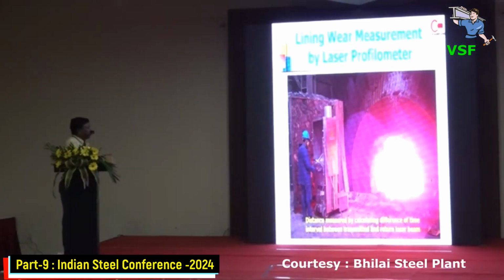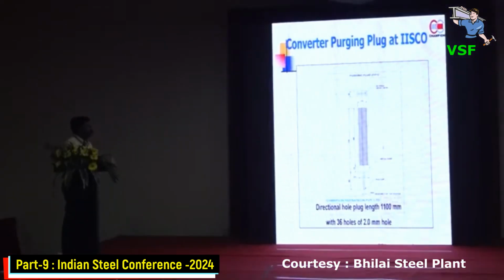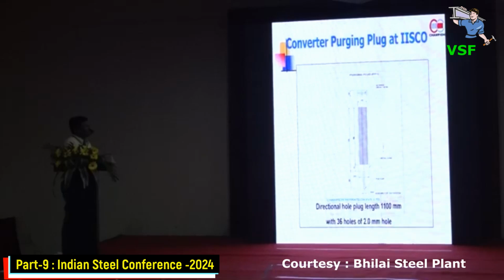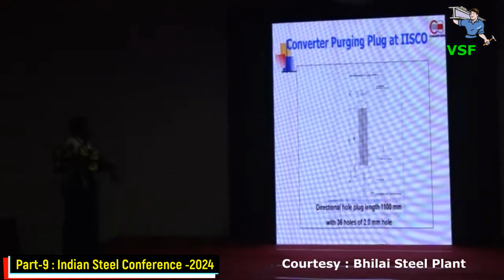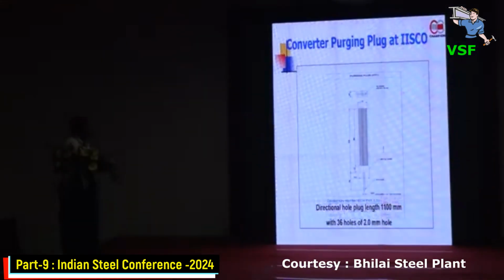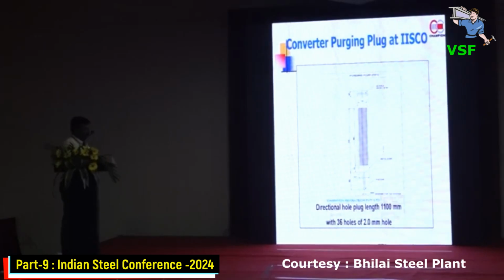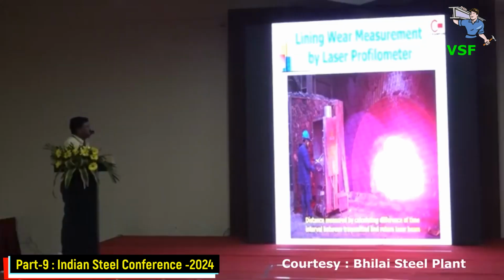So we have targeted some number of sleeves, but as the life is going, we are supplying the sleeves. The sleeve life is around 100 heats. This is the purging element, basically a directional rod purging element. They have 36 purging elements, about 2.0 millimeter, and they have used them up to 3,000 heats. The top and bottom ring after that is converted into the normal top ring.